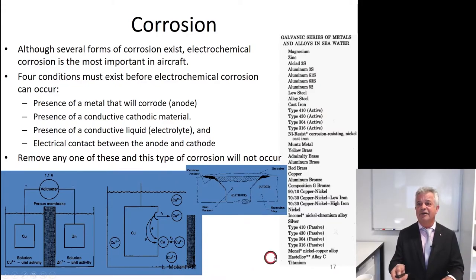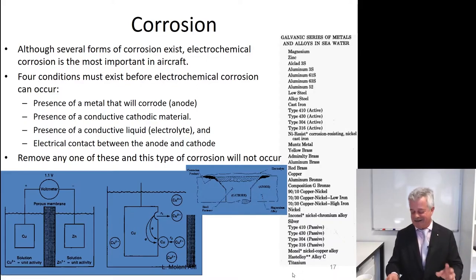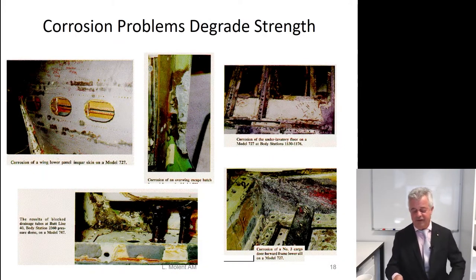Here's our galvanic series down on the right-hand side here. And if I was to put, say, magnesium alloy against titanium alloy, you could basically hear it sizzle away and corrode in your presence. So great care is taken to not have dissimilar materials in close proximity, otherwise you will have yourself an unwanted battery situation. This diagram here is just to show you that it can really be problematic if it's not detected and remedied. These are very severe cases of corrosion.